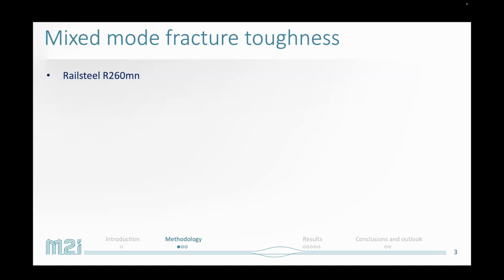So my methodology of doing these fracture tests has 3 phases. First, I'm doing the pre-cracking phase. So we have made, sorry, we'll also introduce these first. So I'm using, as introduced on the first slide, R260MN rail steel, which is a commonly used steel in the Netherlands and all over Europe.